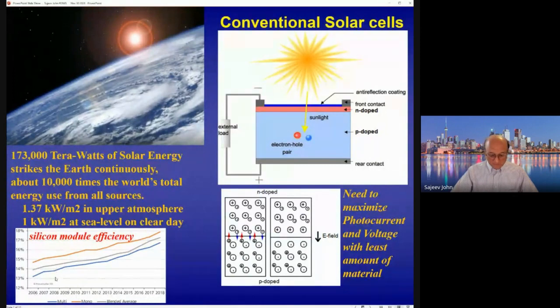Now, solar cells have been studied for quite a long time, and for example, if you see on the left-hand corner here, silicon module efficiency has been increasing over the past couple of decades, and the lines here correspond to the change in module efficiency as a function of the year. The top curve corresponds to monocrystalline silicon. The bottom is a type of multicrystalline silicon. So at this point, you can expect silicon modules that you can buy which have an efficiency on the order of 19 or 20%.